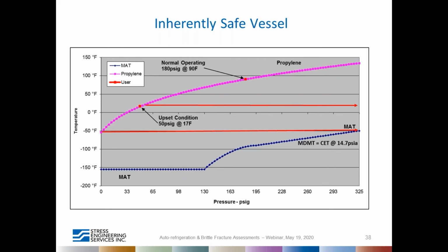So for example, this MAT curve is plotted for one particular vessel that's operating at 180 psi at 90 degrees Fahrenheit. And the operating medium here is propylene. And if you look at the flash curve, which is about the MAT curve in this case, let's consider one scenario, which is a one-step auto-refrigeration, we call it. So you operate at a normal operation pressure, you depressurize it, and then you repressurize it at this pressure. The metal temperature remains the same.